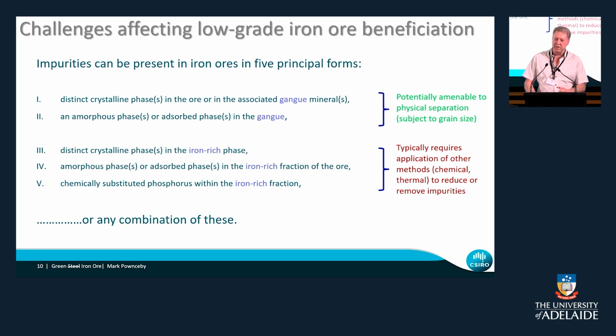The problem arises when you see those grains, like I showed you, those goethite grains where we've got alumina and phosphorus actually within the structure of the grains. And that is a real problem. You're going to have to use some sort of technique that's going to break apart that structure, if you like. And so that's where you're going to have techniques like thermal beneficiation or leaching to really get in there and actually remove those impurities. And we'll get to those again in a little bit.